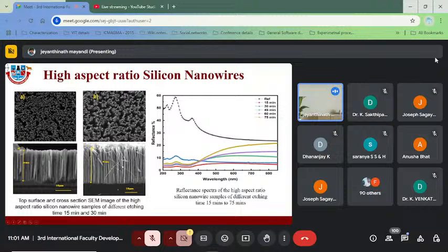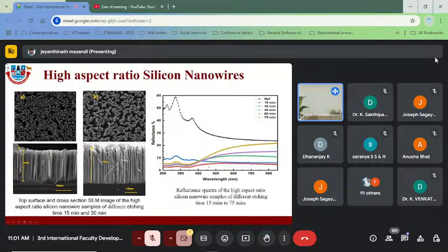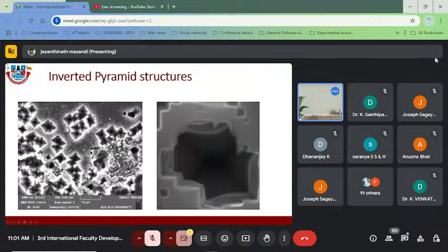And this really has reduced quite a lot. But interestingly, after 30 minutes each, or 15 minutes and 30 minutes each, it started to increase. The reflectance increases because it again polishes some of the layers. And another important aspect of making an inverted pyramid or black silicon.